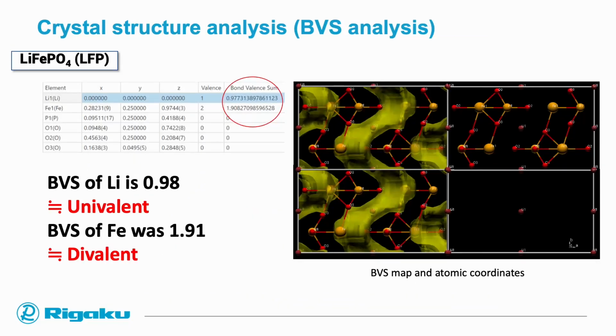On the other side, we can also use this information to calculate the bond-valence sums, which are important when it comes to the storage capability of lithium ions within our battery material. And with the help of our software, we are able to calculate the bond-valence sums, but also depict them, as you can see to the right. In this special case for lithium iron phosphate, we see that, for example, lithium was found to be univalent, and on the other side, iron was found to be divalent.